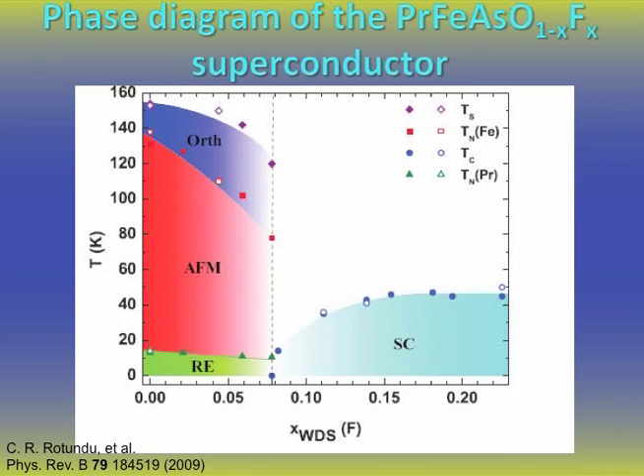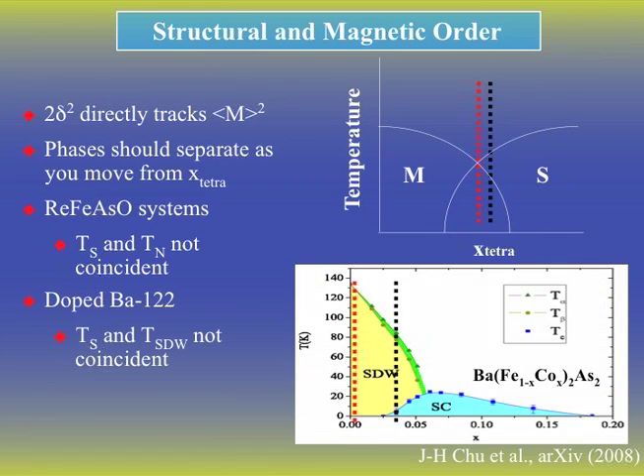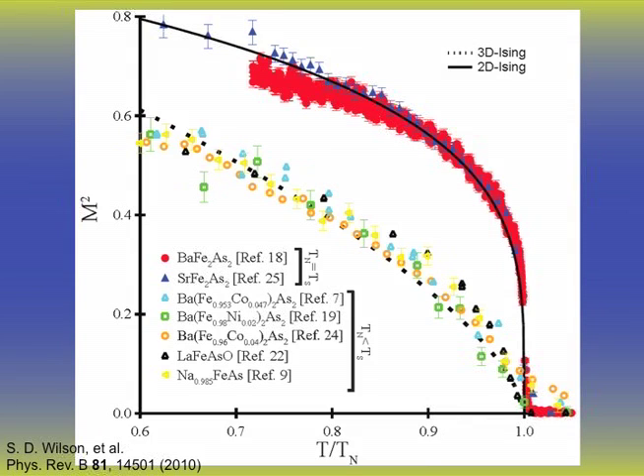This is our own work on the phase diagram of one of them, and I'll only point out that you get a magnetic state and then a superconducting state, and the topology of the phase diagram is closely similar to that of the copper oxides. And then this shows in a particular material also, a phase diagram which is again closely similar. This is not our work, this is work again done by a Chinese group, except for one real peculiarity, which is you can see right near the crossover point, there's a range in which the material has a structural phase transition, a magnetic phase transition, and a superconducting phase transition. And it appears as if the electrons are participating in all of these three phases simultaneously. But generally, we see that, again, you have competing phases with magnetism competing with superconductivity.